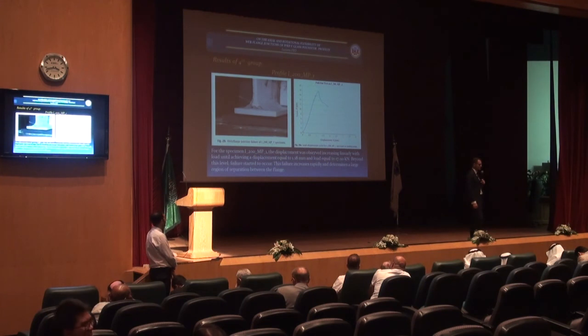But of course, there are also limitations in the percentage of strength that you can give. You cannot go over 50% of the strength. So if you can make safe structures, improving the strength by less than 50% is okay; otherwise you cannot use FRP. Also, due to the creep behavior, we don't know what will happen after 30 or 40 years to the interface between the plate and the concrete cover. So this is an open question, and for this reason we are continuing to study the creep behavior of this application.